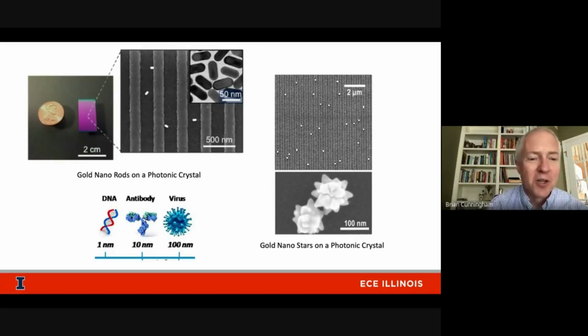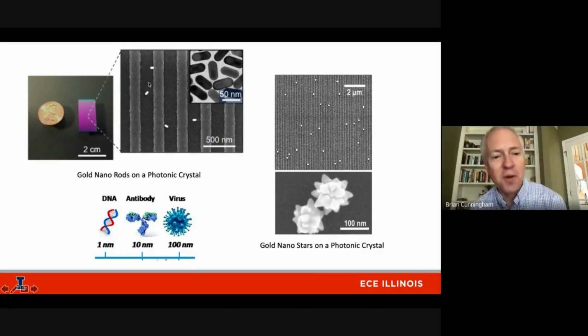And so in doing so, we can do some very interesting things and develop some new forms of microscopy like I alluded to. Just to show you an idea of the size scale, here's one piece of a photonic crystal wafer. This is a wafer actually originally made on an 8-inch diameter piece of glass, chopped down into die. Here's one around the same size as a US penny. This whole surface is a photonic crystal. If we zoom in with an electron microscope, we can see a photonic crystal surface with a few gold nanorods sprinkled on it. Here are some gold nano urchins, which have this spiky surface on the outside. These nanoparticles are very small, around the same size as a virus, around 100 nanometers in diameter, not too much bigger than a protein molecule, such as an antibody. And to further give you scale, here's a DNA molecule at around 1 nanometer size scale.